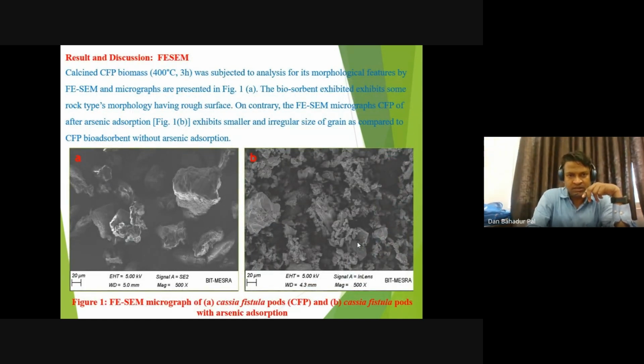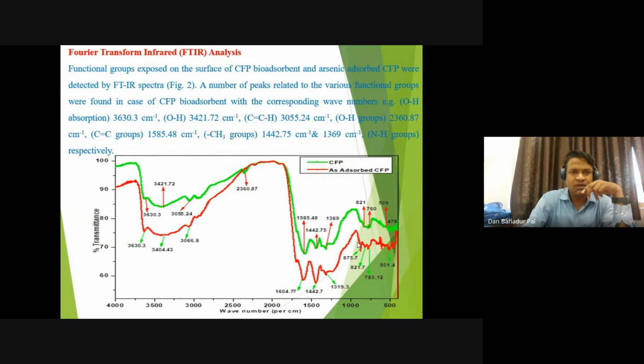First, we check the morphology before the adsorption and after adsorption. Before adsorption the nature is like lumps, and after adsorption the morphology of the sample changes. Next, we characterized the functional groups, also before adsorption and after adsorption. The blue one is before adsorption and the red one is after adsorption. Some functional groups change location during the adsorption of arsenic 3.